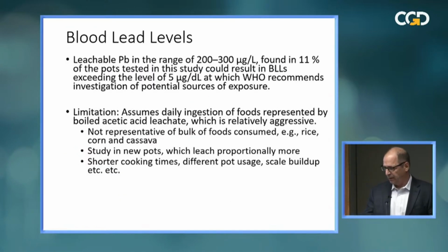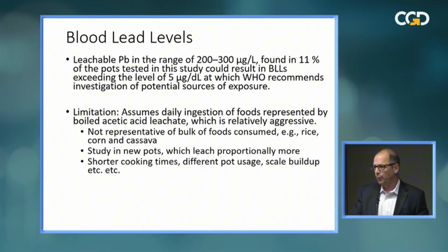So there's a lot of limitations in what we did, especially with respect to the modeling. We're modeling this based on acetic acid, which is acidic. It's supposed to represent a tomato sauce. What it doesn't represent is rice cooked in the pot, cassava, other staple goods that form the predominant diet of most people. So leaching with acetic acid, boiling it, is great to certify a pot is safe under most conditions, but it's probably very poor at estimating what actual exposure is based on actual dietary consumption.